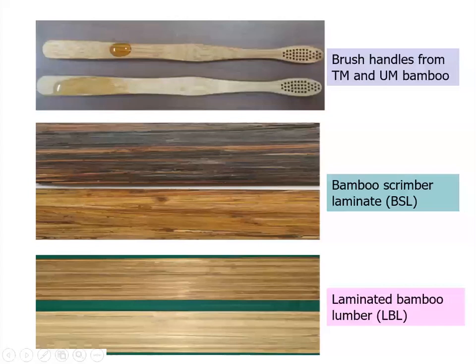Here is the method of doing that, an efficient utilization method to convert pre-softened bamboo. First we take the bamboo, make it soft, try to open it up, and then use the press to slightly densify it and make it flat. So this is a relatively simple technology with a high material utilization rate.